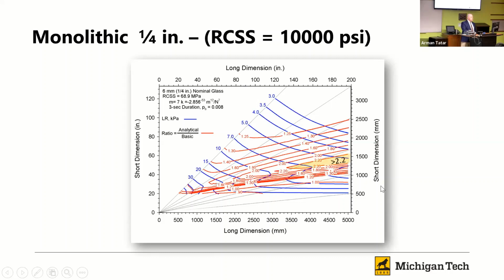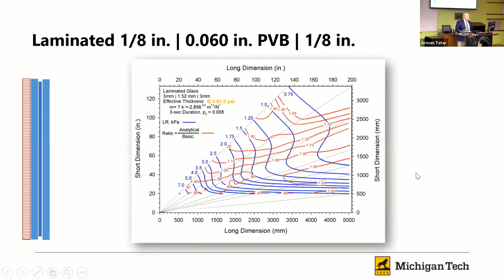So we're seeing similar contours, in this case, up to a 2.2 times difference between the two of them. And so that means that, according to this analysis, this piece of glass is 8, almost 9 times stronger than just regular annealed glass, okay? And that's at the minimum. It'll go higher if the RCSS is a little bit higher as well. Again, same principle. They don't leave it at the minimum. They usually go a little bit higher than the minimum to guarantee they don't have one slip through that drops below that. So I'm going to go through these a little bit quicker.